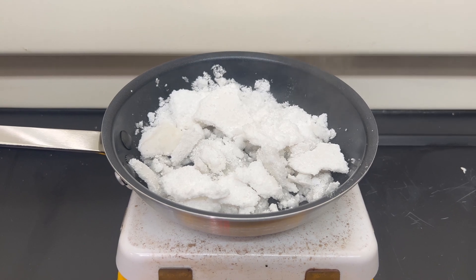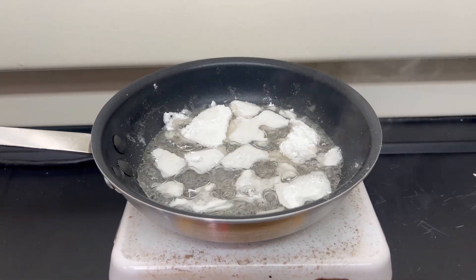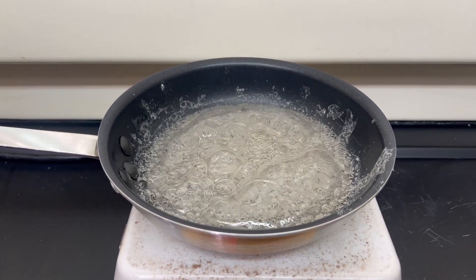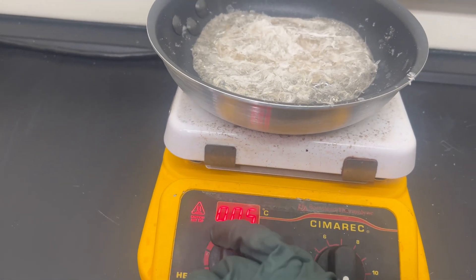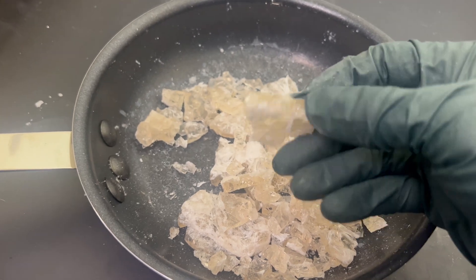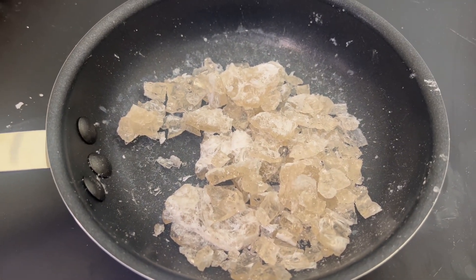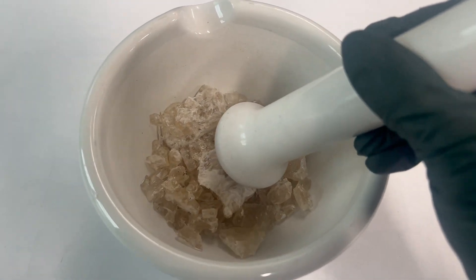It was easy to stir, and over the course of an hour, all the oxide became clearish. As soon as the bubbling stopped, this meant the reaction was over. The bubbling is caused by release of water from the reaction. The boron trioxide, even though it was on a non-stick pan, stuck a little and had to be removed with a scraper. The boron trioxide is then collected and ground up into a powder — this part took the longest.